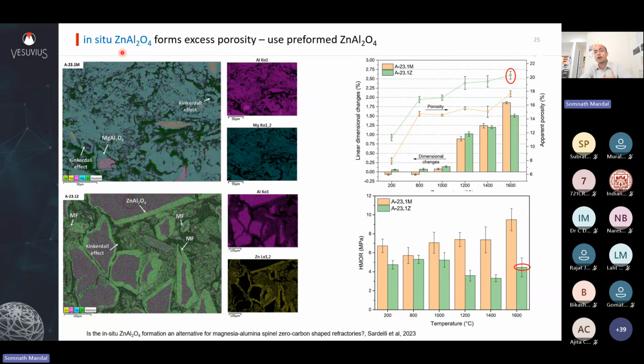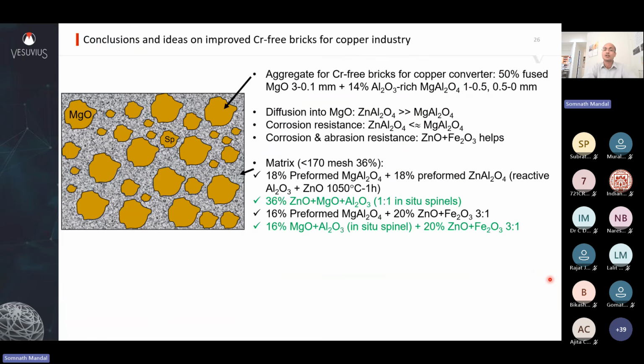People who have tried to have a lot of in situ zinc aluminate end up having a lot of Kirkendall porosity, which is basically because the diffusion rate of zinc is very high compared to alumina, and you end up with lots of vacancies, pores on the zinc side. And you see the zinc diffuses into the alumina aggregate, but then it leaves behind pores. So you have to optimize, and the best is to use a preformed spinel. If you use too much of this in situ zinc aluminate, you end up with a lot of porosity, higher porosity than magnesium aluminate, and then lower hot strength, which is never good for a refractory.